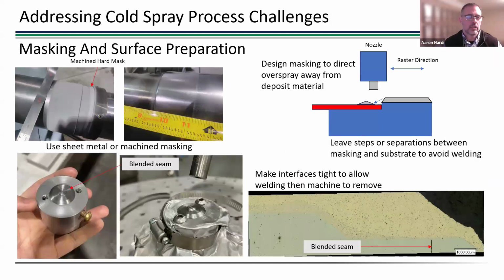All right. When we start talking about masking, here's just a couple of examples of the way it can be done successfully. So the upper left, you see a shaft. In this case, we're applying a material to that shaft, and we have a piece of hard masking adjacent to the land that we're depositing. Now, what's important to note, and it's tough to see there, is that that piece of machined masking is smaller in diameter than the diameter that we're coating on, so that those two don't bridge. We don't want them to weld together. So we actually make it a little bit smaller. And now, similar to this image in the upper right here, any deflected particles are actually deflecting onto the masking rather than deflecting onto our deposit material. So that's kind of one way to think about addressing that.